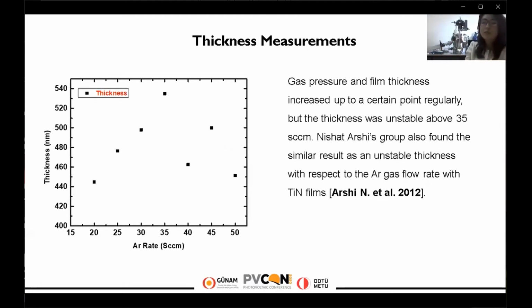For 40, 45, and 50 sccm, thickness is not stable. Actually, this is very similar to the Nishat Arshis group study, because they also found similar results, an unstable thickness with respect to the argon gas flow rate with titanium nitride films. So we can say that gas pressure, argon flow rate affects the thickness, but it doesn't look regular in this graph. But according to other studies, for example, Musab Salman Sultan's studies, he also studied the effect of argon gas rate on his devices.